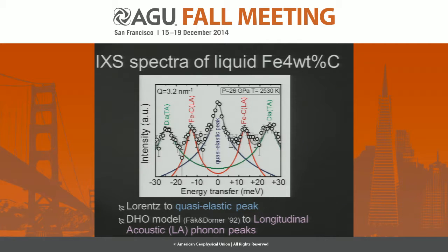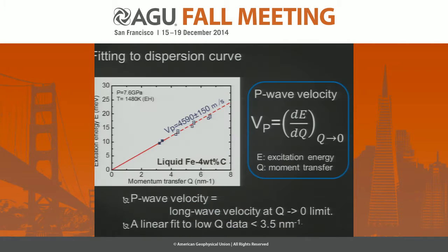For the acoustic phonon modes, you can see a double peak, in the positive Stokes side and in the negative anti-Stokes side, with the same energy. After fitting, we plot the excitation energy for the sample as a function of momentum transfer.